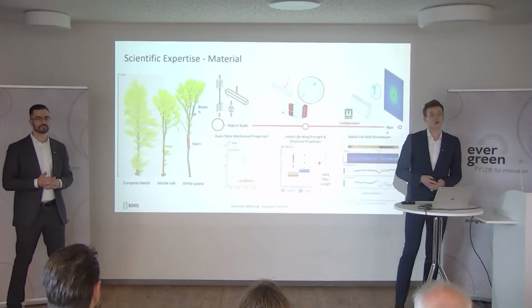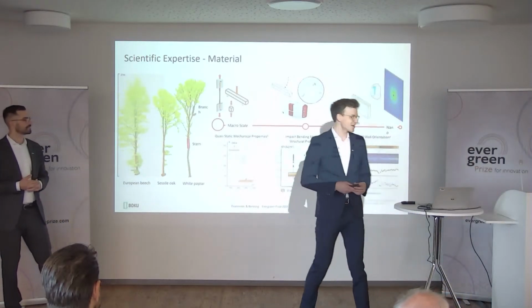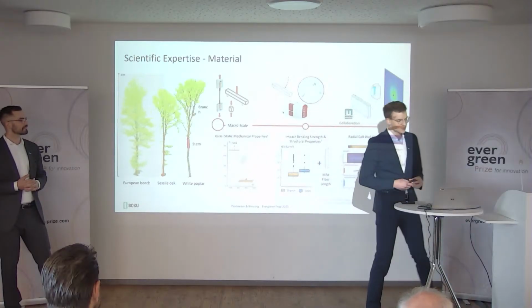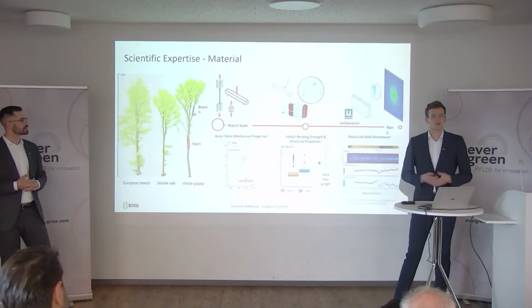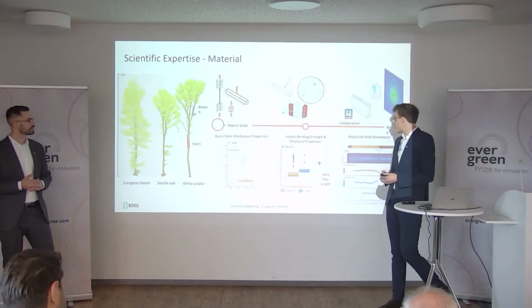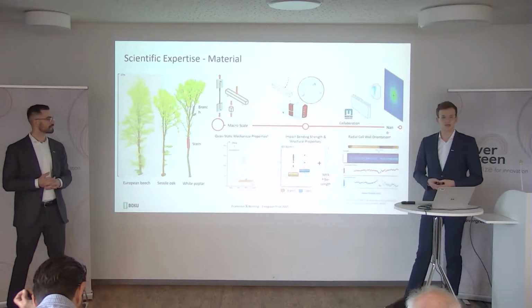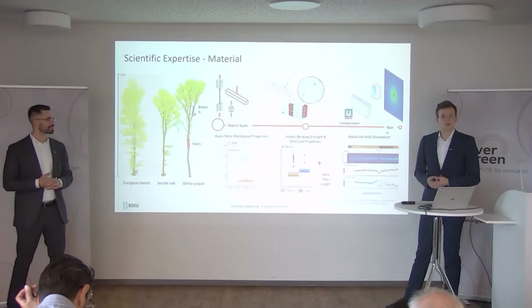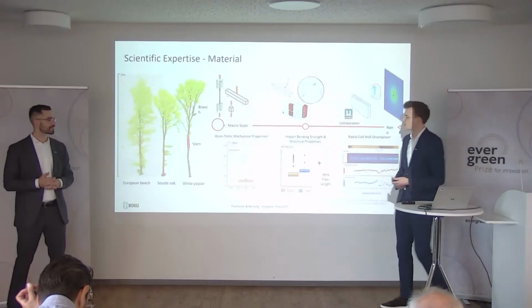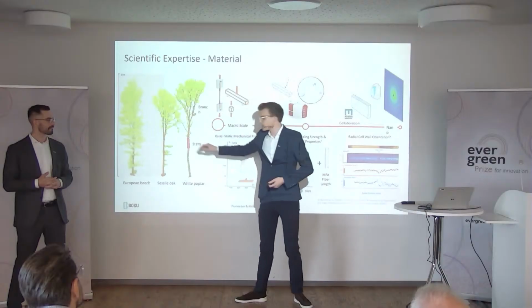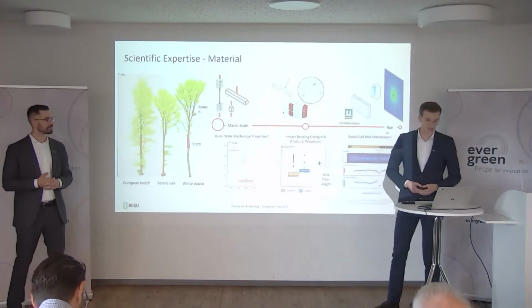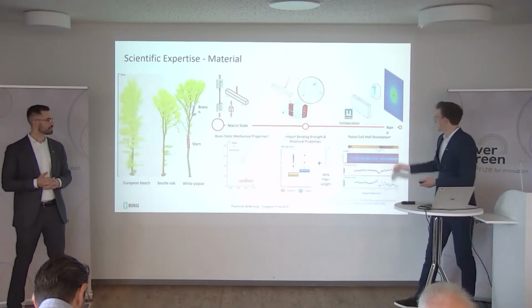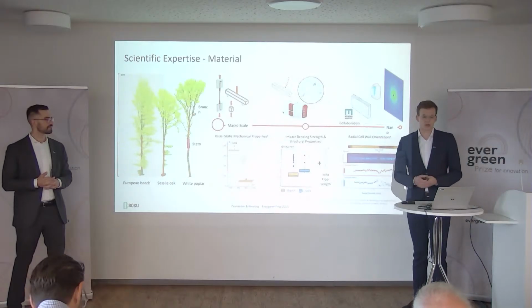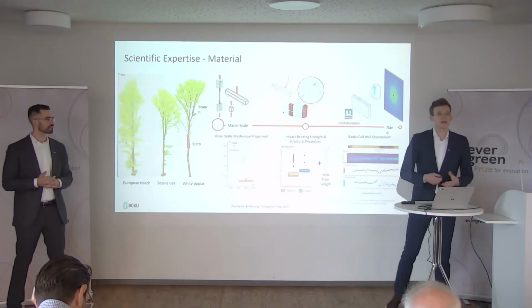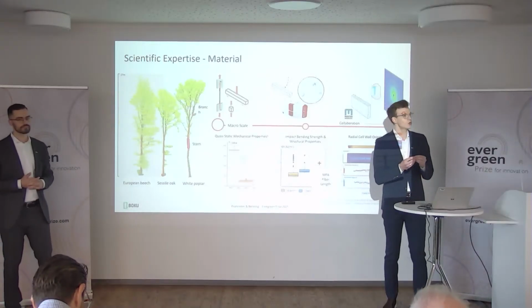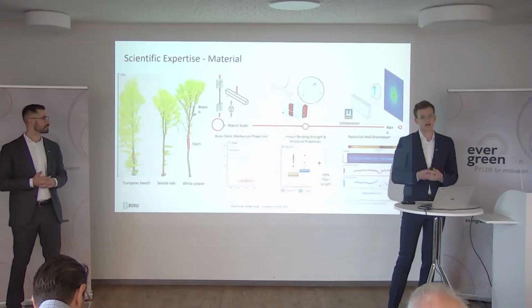And then the most recent, and also for me the most exciting part happened some months ago. Again, collaboration with physicists from BOKU. We went together to the synchrotron particle accelerator in Hamburg, and we looked into branchwood on the cell wall level. We again compared steep branches and flat branches to the corresponding stem wood, and very exciting to me, there are differences also depending on the growth angle. And overall, flat branches for oak, for example, had the highest overall orientation on the cell wall level, also higher than the stem.